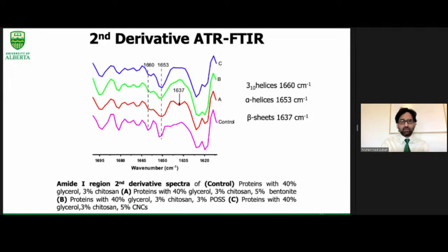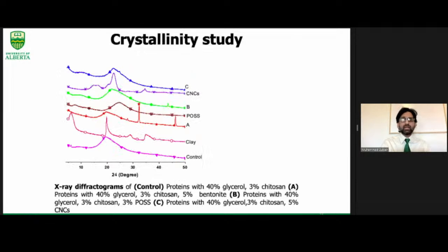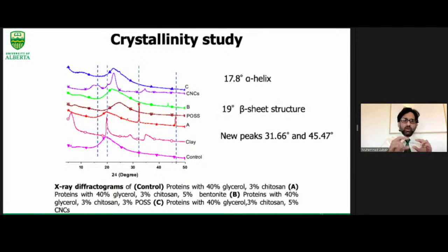We also did XRD. XRD was performed to see the crystallinity patterns of the proteins after the addition of the nanoparticles. The first peak around 17.8 belongs to the alpha helix, and the second peak, that is around 19, a beta sheet structure. While in case of nanoparticles, we can see that new peaks appeared. So it means new types of interaction have been produced between nanoparticles and the protein structure. And also there is the disappearance or the shifting of the peaks, which shows that the crystalline pattern of these proteins has changed after the addition of nanoparticles, and new types of interactions have been developed that might be the reason for the increase of the physiochemical properties of the films.